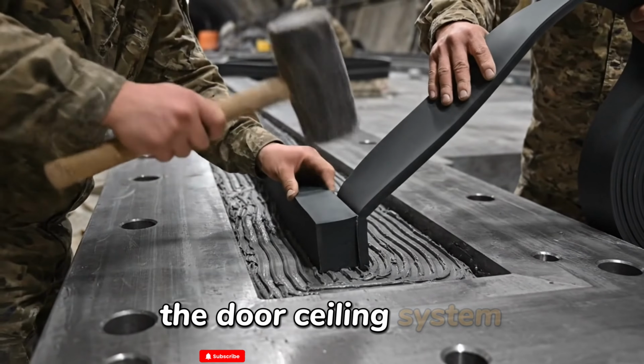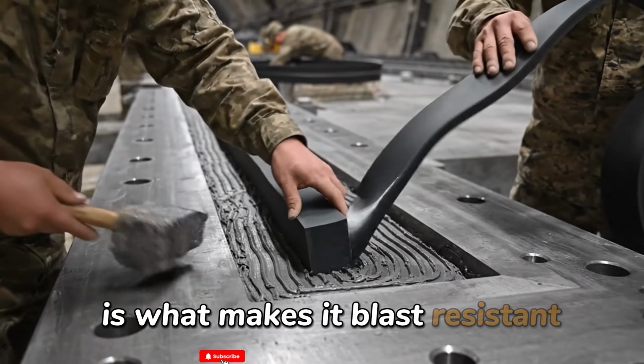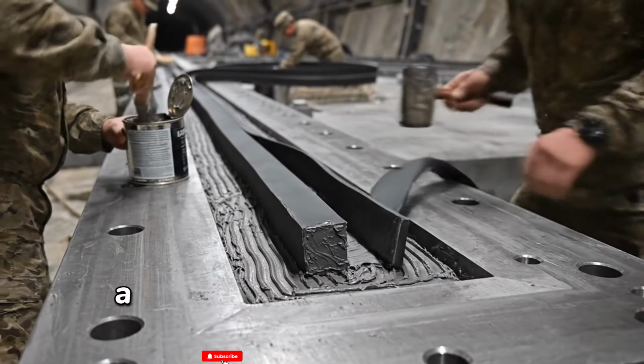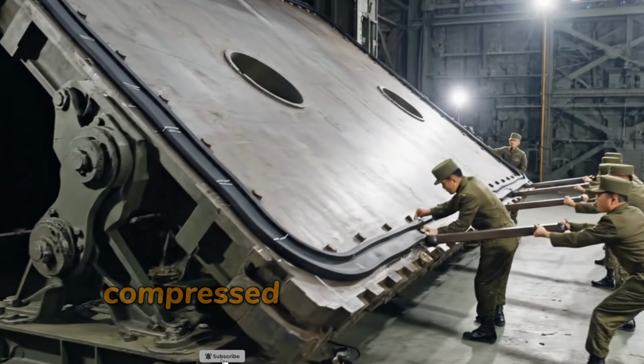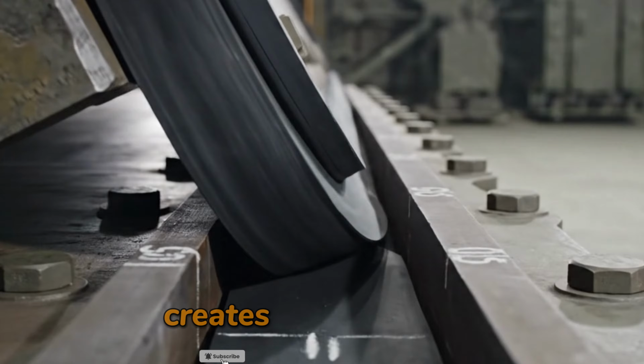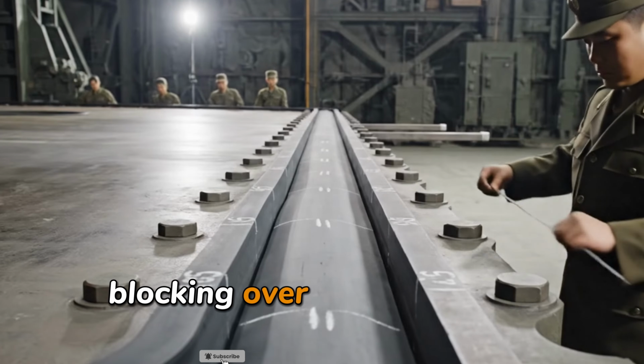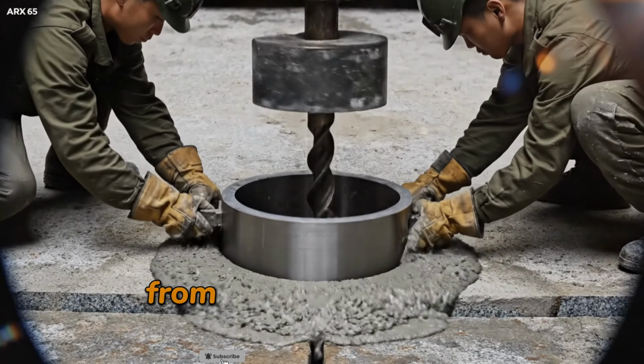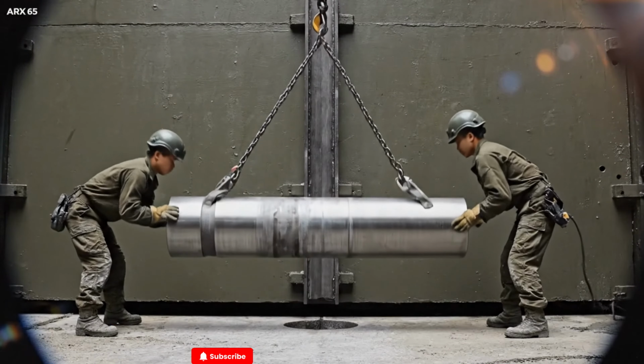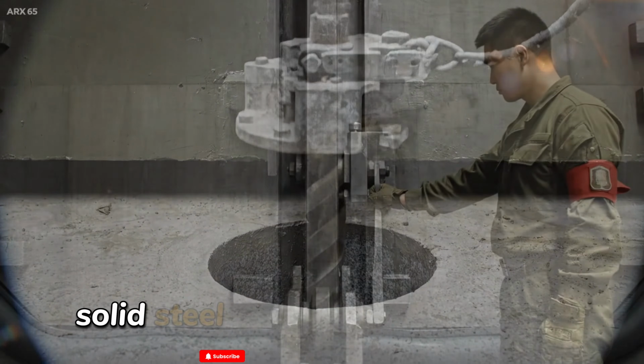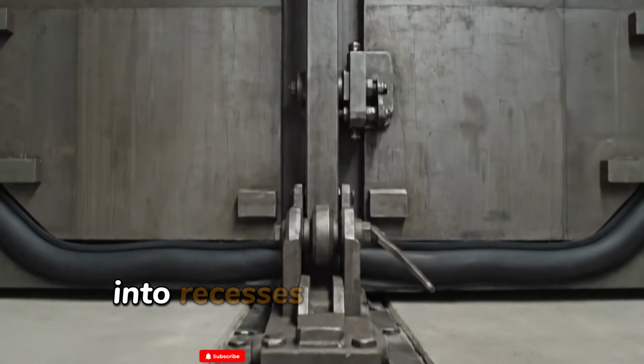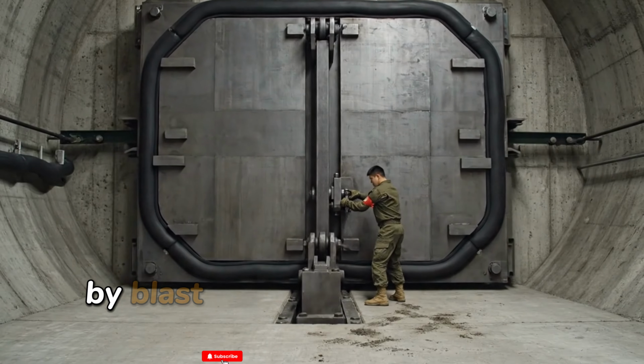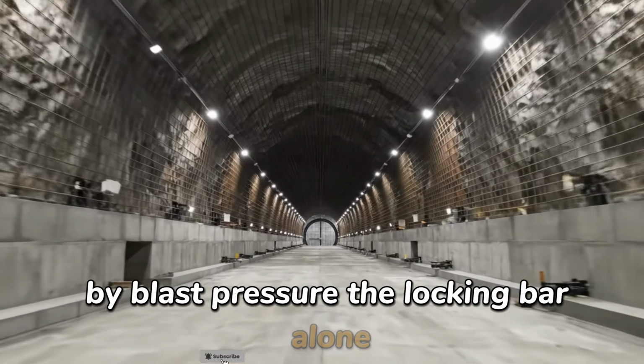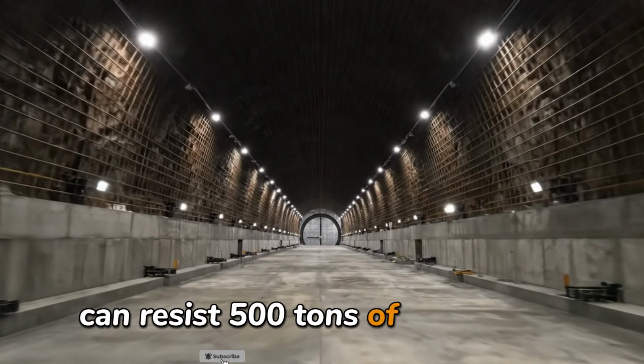The door sealing system is what makes it blast resistant. When the door closes, a 50 millimeters thick rubber gasket compressed between the door face and the frame creates an airtight seal, blocking overpressure waves from a nearby explosion from entering the tunnel. Additionally, a drop bar locking mechanism, a 100 millimeters diameter solid steel bar that drops vertically into recesses in the floor and ceiling, prevents the door from being forced inward by blast pressure. The locking bar alone can resist 500 tons of lateral force.